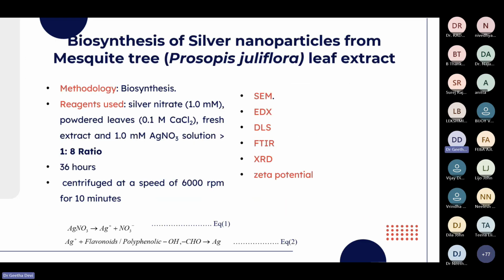And also we have synthesized silver nanoparticles from mesquite tree leaf extract. Mesquite tree is a common tree in Oman, and this is a very dangerous tree. So we have utilized this tree extract for the synthesis of silver nanoparticles, and the methodology employed is biosynthesis using silver nitrate and the extract.